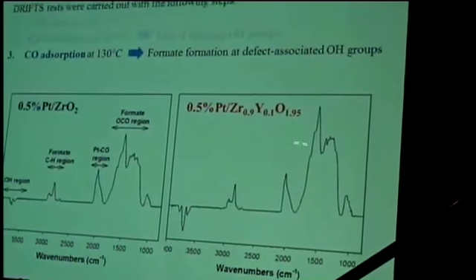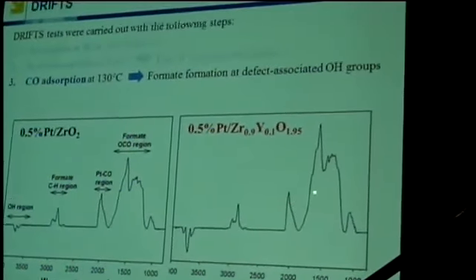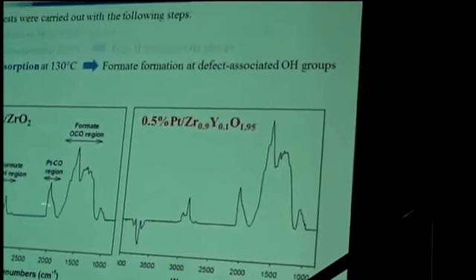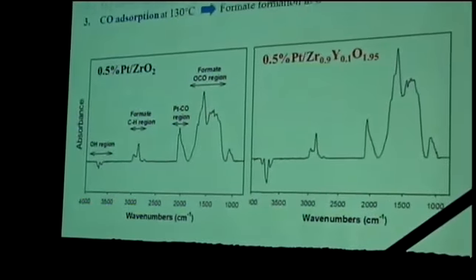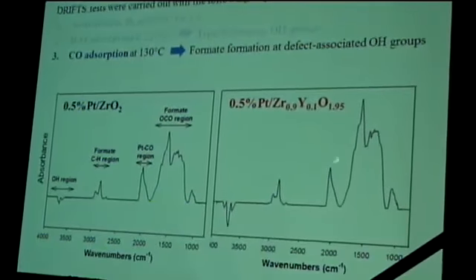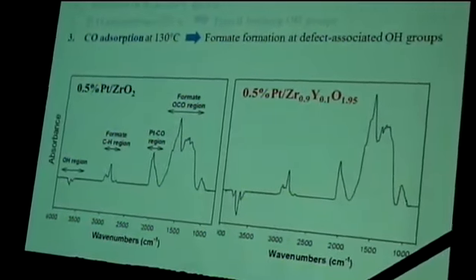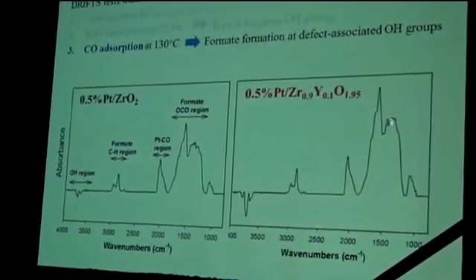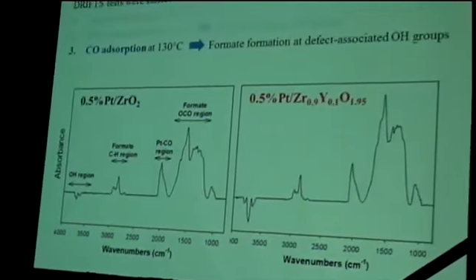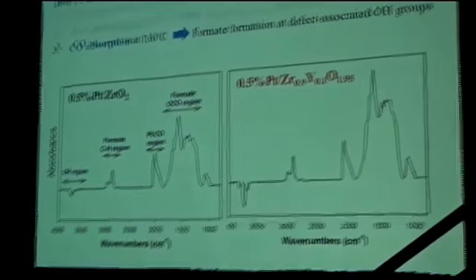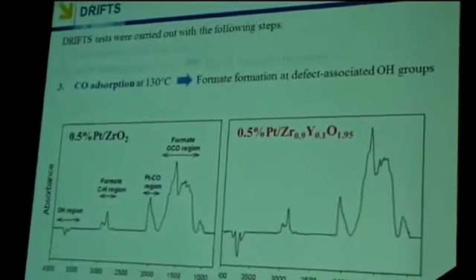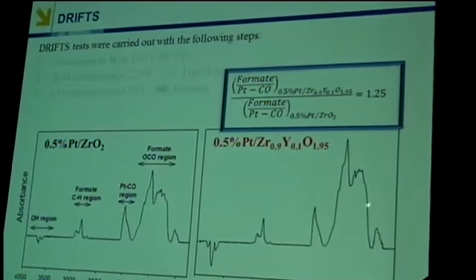And what we see is here's the yttria-doped catalyst. We see that the formate CH stretching and the OCO asymmetric and symmetric stretching bands are significantly higher than on the undoped catalyst. And here you can see the platinum CO is pretty much the same on both catalysts. So the results suggest that we did indeed increase the number of defect sites in the yttria-doped catalyst, and we have a higher density of the defect-associated OH groups. We take the ratio of the ratios, formate to platinum CO, for yttria-doped over undoped. You can see the increase here.